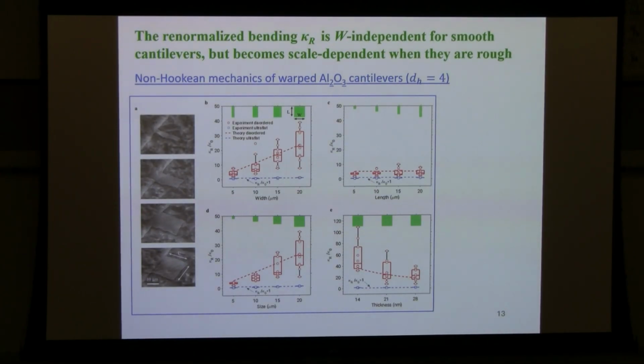And so here's some of their results. These green things are the dimensions of the diving board. You can do it as a function of the length of the diving board, and then the expectation is because the width is always constant, that's what controls this anomalous elasticity. The elastic constant doesn't matter. The blue is the control. That's from the smooth side. The other side is from this other data. This red data is from the rough side. And now you can see that if you just do the standard textbook measurement of a renormalized bending rigidity, renormalized by these ripples, it's scale dependent.